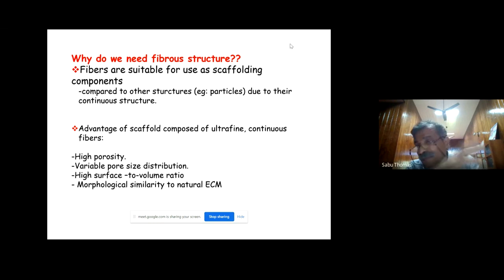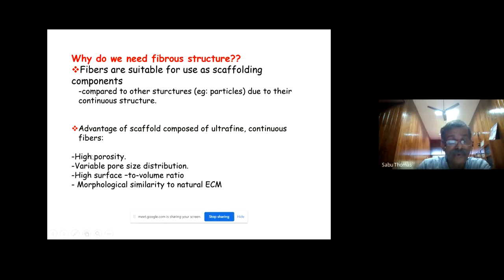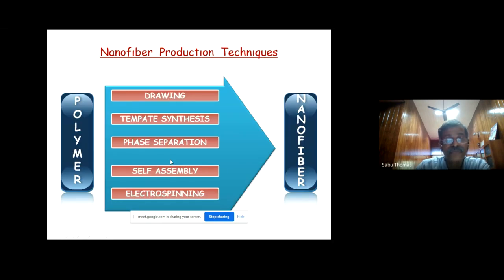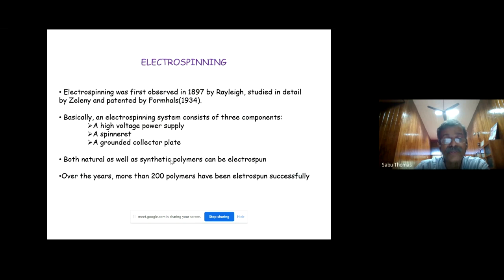Then you might ask, in many of our structures, we use electrospun systems. Electrospun systems give rise to fibrous structures. Fibrous structures have a lot of advantages: high porosity, variable pore size. You can have orientation in fibrous structure. So how do you make these fibers, nanofibers? You can produce them in different ways: drawing process, template synthesis process, phase separation process, self-assembly process, electrospinning process. We make fibers particularly by the electrospinning process.